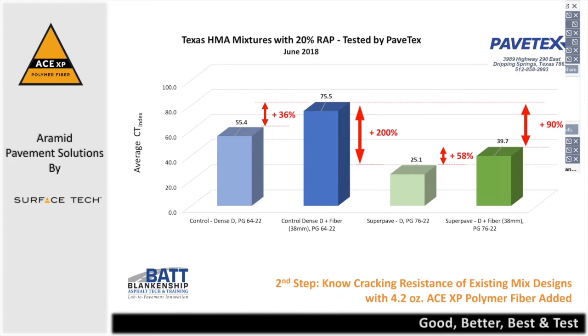And if there was ever a reason why, you're seeing it here on the screen. So you have a 25.1. Now, keep in mind, Fuji was suggesting for Texas for that number to be 65. Neither one of these two mixes that we tested out of the lab hit that minimum number. And of course, when we added one dose of 38 millimeter ACE XP polymer fiber to that, we got that number to go up nearly 60%.